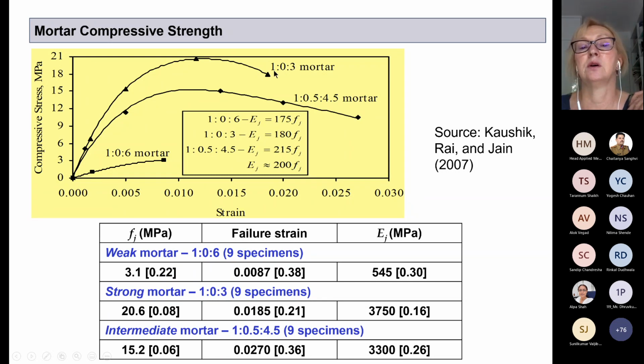So this 1:0:3 is the strongest mortar, and this one with some lime, you can see that it has the highest strain before it fails. So it has the highest ductility, as some colleagues like to call it. And you can see how this typical Indian mortar 1/6 cement sand is the weakest, and it has very low strain before the failure. So this is very important.